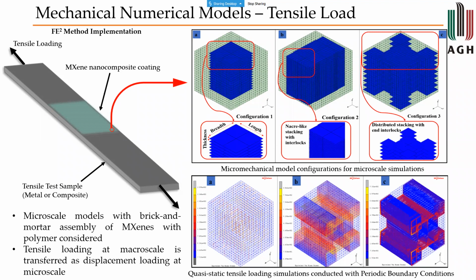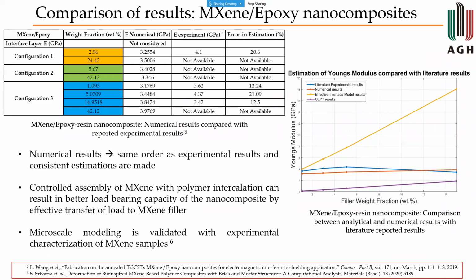So our target was to model this, and we did come up with some deterministic models to start off with. Out of these, we also looked at how intercalation or mixing of MXene with polymer would affect the models, where you would have different distances between the flakes and multilayers, which would also contribute to the variation in their mechanical properties here. We also subjected them to the Hill-Mandel condition.